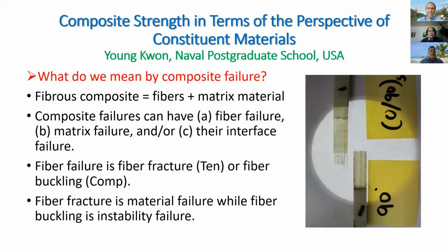On the other hand, if you apply the load in the transverse direction of the fiber, then fiber doesn't fail, but matrix and interface are going to fail. And even delamination is also the matrix failure and/or the interface failure. So anyhow, those failure modes can be simplified in terms of those three basic failures at the constituent material level. Also, if you look at the failure of the unidirectional composite in tension, the fiber is going to fracture eventually. So this is what we can say is the material strength of the fiber.